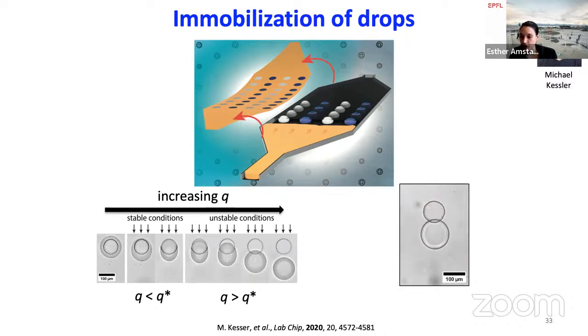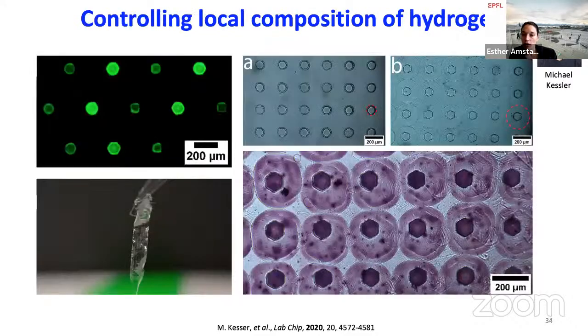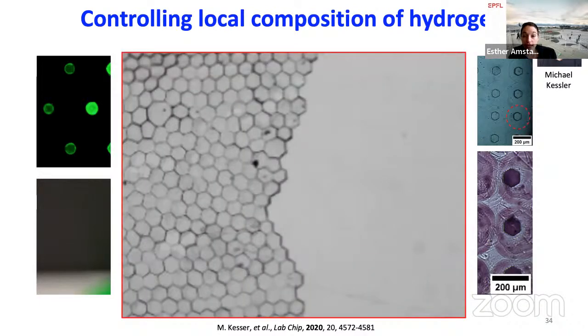And we took advantage of this feature. We studied how the size and the shape of these traps influence the trapping force, and we took advantage of that to design different types of traps to actually control which drop goes where. And thereby we could gain a true control over local composition of our hydrogels. But even though we could get this local control over the composition, once we mechanically tested our hydrogels, we were a bit disappointed because they broke again in a very fragile manner, because the interparticle connections were weak. Actually, I don't think they were weak, but the cross-linking density was just so low that we broke them very rapidly.